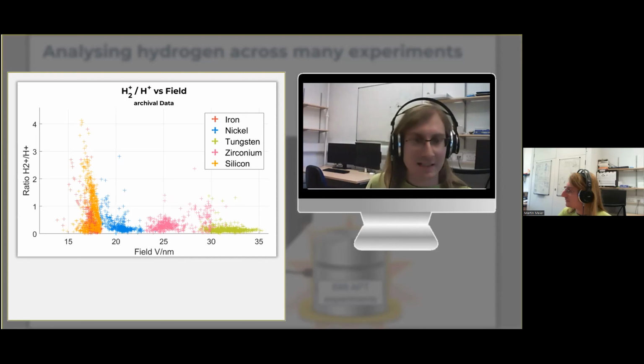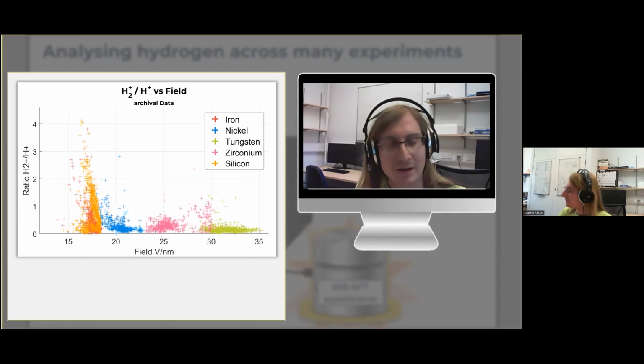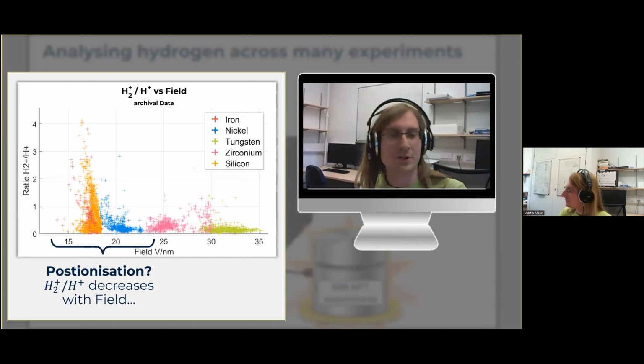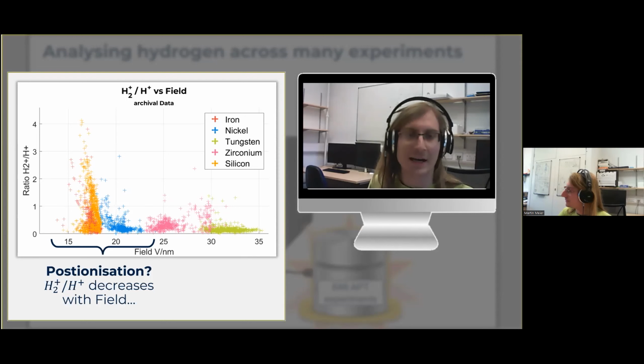It seems like there are two regimes to this diagram. Firstly, there is this low field regime, which goes up to about 25 volts per nanometer. And what we see is that as the electric field increases, the hydrogen ratio decreases. My spontaneous guess is that this is down to post-ionization. So we might be evaporating H2+ out of our tips, but this might then post-ionize and dissociate into 2H+. And this could explain why we're seeing a decreasing ratio, which corresponds to that shift away from H2+ towards a H+ peak.